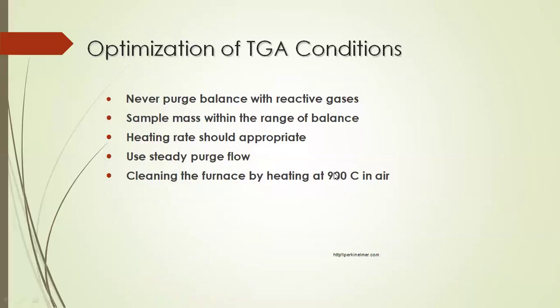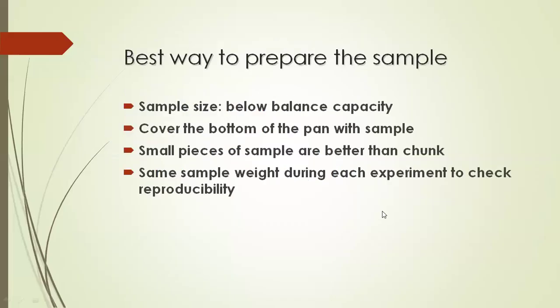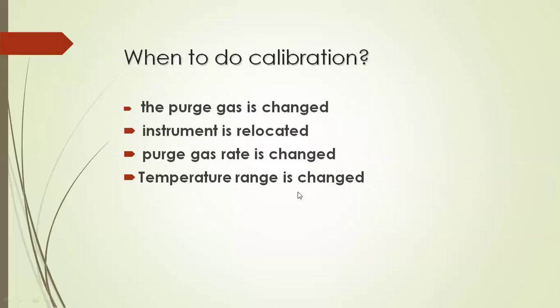How do you optimize the TGA conditions? Never purge the balance with reactive gases. Keep the sample pan within the range of the balance. The heating rate should be appropriate. Do a steady purge, and always clean the furnace by heating at 900 degrees centigrade in air. As we have already talked about, if your sample is very volatile, then always cover your sample pan with the cover. Use small pieces, as we have already told you.